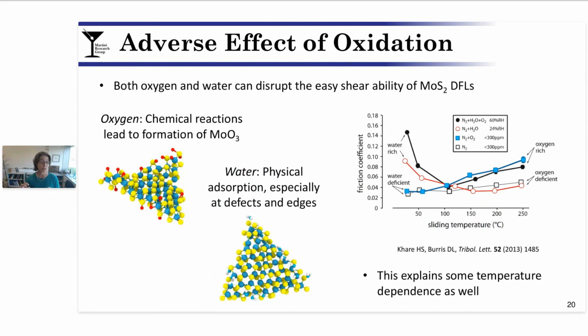Water physically adsorbs to the MoS2, particularly at defects and edge sites. Both of these are disruptive and therefore can explain the observed poorer performance in humid conditions. However, oxygen and water interactions can also explain some temperature dependence.